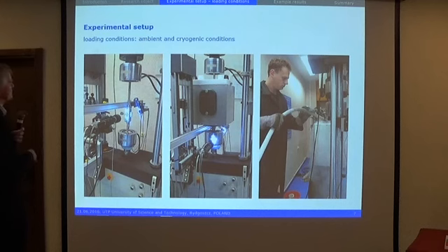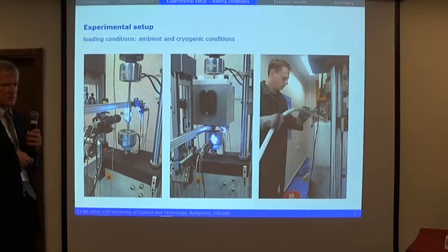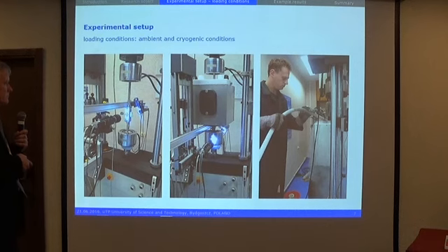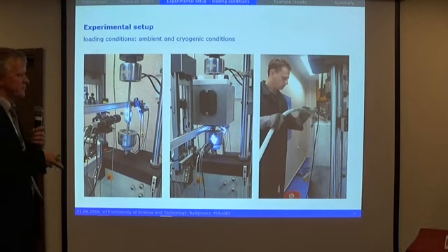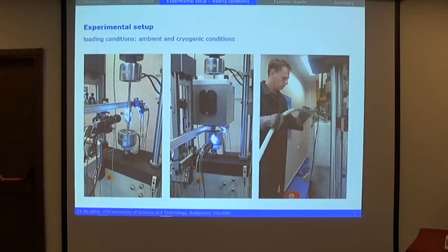Some words about our experimental setup. We have used a typical fatigue testing machine, but not typical was the chamber, which gives us the possibility to use liquid nitrogen. All things, specimen, grips, and other equipment elements were immersed in the liquid nitrogen, which gives us the required temperature condition. And here is the process of filling the chamber with the nitrogen.